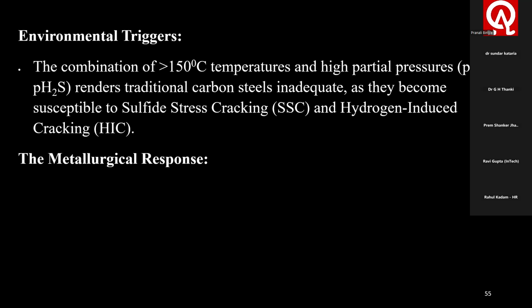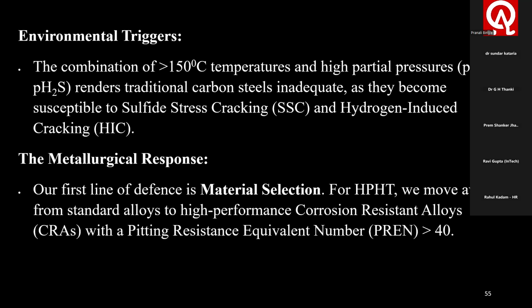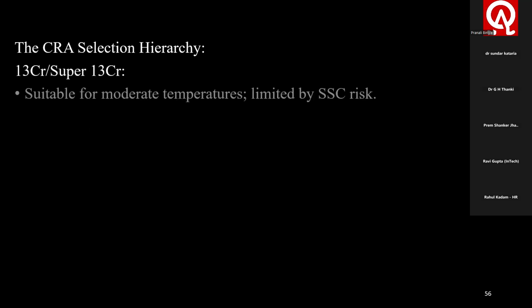The metallurgy response. Our first line of defense is material selection. For HPHT, we move away from standard alloys to high-performance corrosion resistant alloys with a pitting resistance equivalent number of more than 40. In this, what will you see in the hierarchy? 13 chromium to super 13 chromium. It is suitable for moderate temperature, limited by SSC risk. You have to be careful, the SSC risk is definitely prevalent there.